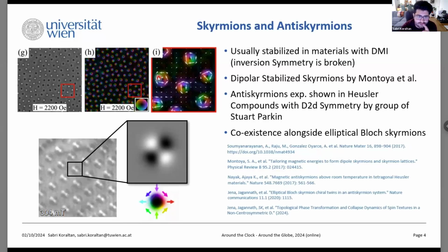So what's the anti-skyrmion? If you look at the skyrmion above, this looks like a vortex. I guess you're familiar with the vortex structure, so it's just a circulation. But the vortex is in-plane, whereas the skyrmions are out-of-plane textures. And the anti-skyrmion is the topological counterpart to the skyrmion, and it has an anti-vortex-like structure. So the domain walls enclosing the skyrmion core follow this anti-skyrmion-like state.